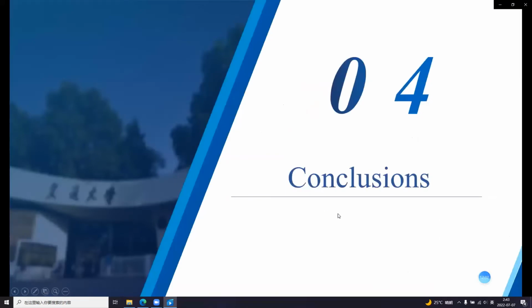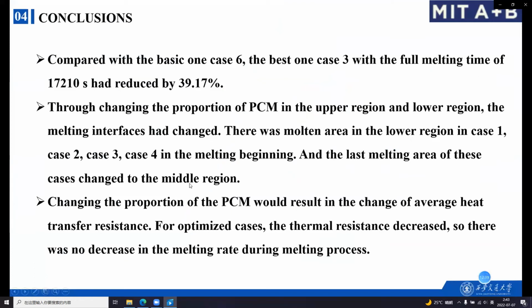And the last part was the conclusions. From this research, we could get 3 conclusions. The first conclusion was that, compared with the basic case 6, the best one, case 3, with a full melting time of 17,210 seconds, had reduced by 39.17% through changing the proportion of PCM in the upper region and the lower region.